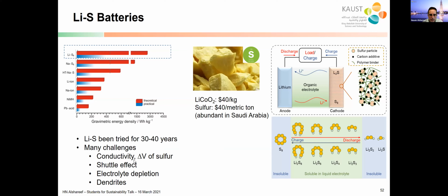Number one, the sulfur is not conductive. It's somewhat insulating, so you have to add a lot of carbon in the electrode. And now this carbon is not active, so you lose a lot of active material. The sulfur also experiences about 80% volume change, and this volume change can also degrade the cathode and the battery lifetime.